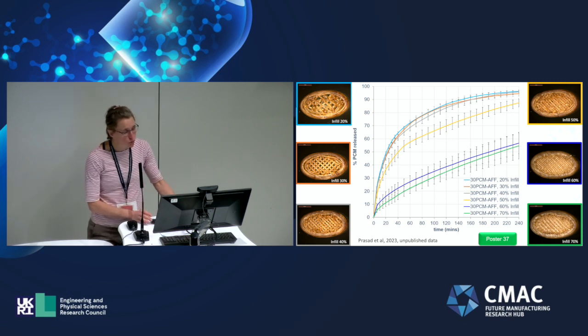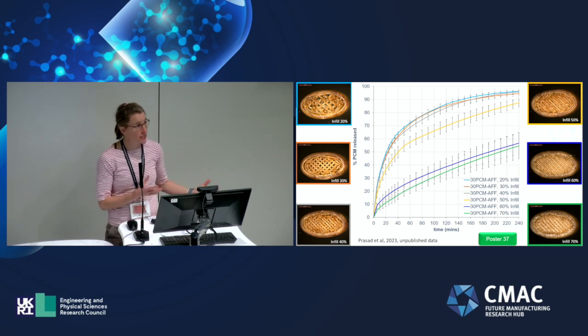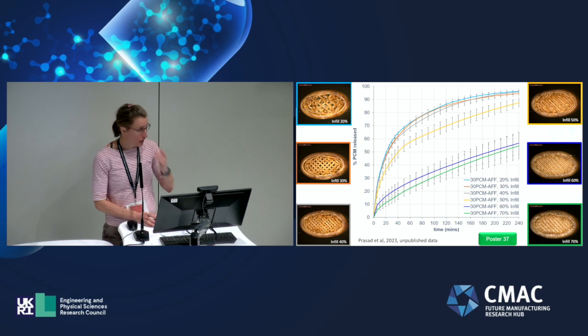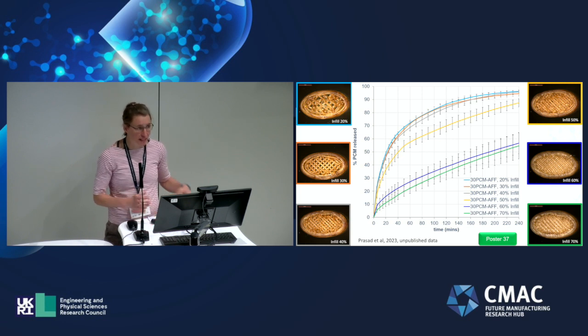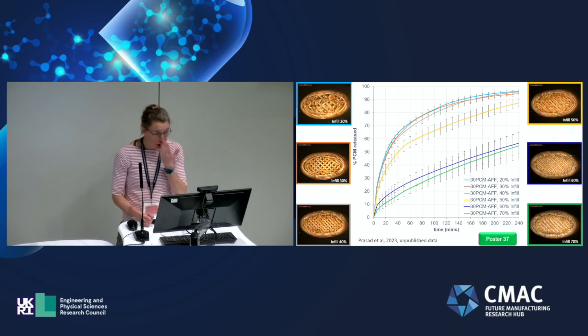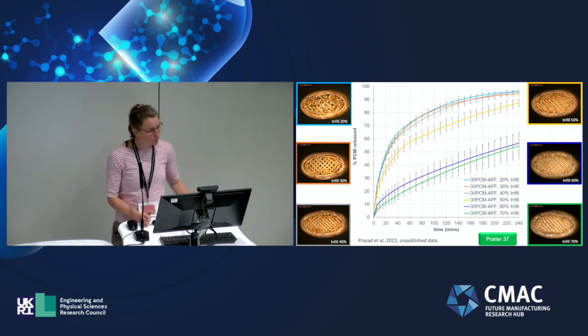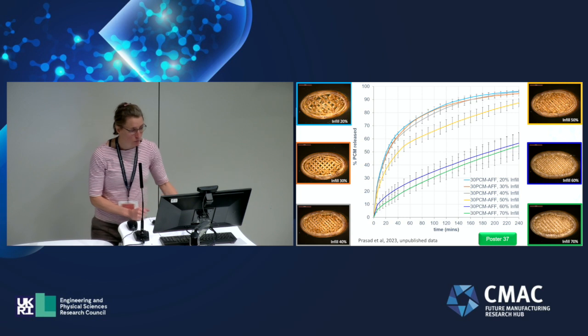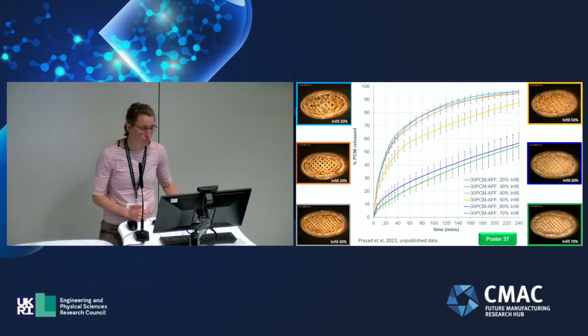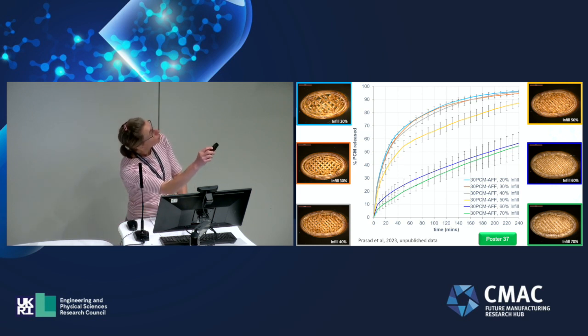This slide relates the microstructure of the tablet to the dissolution profile, the product performance of these tablets. Again, this is the example of the 30% paracetamol drug loading in HPMC. HPMC is a polymer that tends to swell quite a lot when it comes into contact with aqueous media. And what we can see here is that on the right-hand side, the low infill percentage tablets all showed a very similar release profile. That's here at the top.